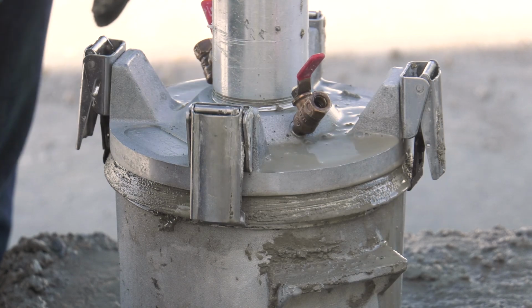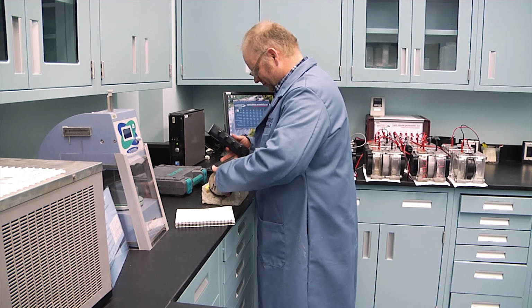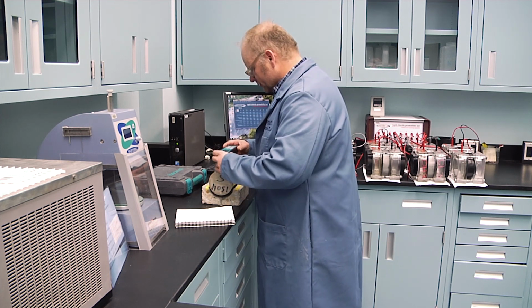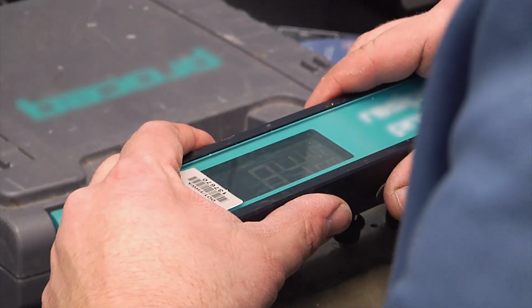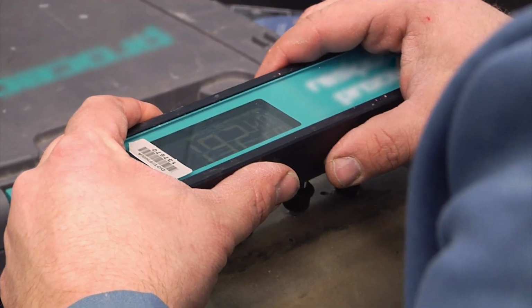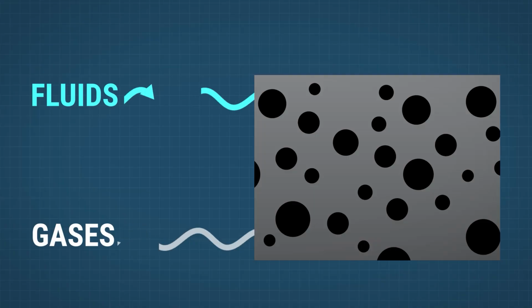There are a lot of tests that you could run for durability. So I'm going to just talk about two that are very field-friendly and two tests that are actually being used by a lot of DOTs right now, being evaluated right now. Of course, those are the super air meter and the surface resistivity test. The surface resistivity test is used to evaluate the electrical resistivity of water-saturated concrete to provide an indication of the concrete's resistance to chloride ion penetration.